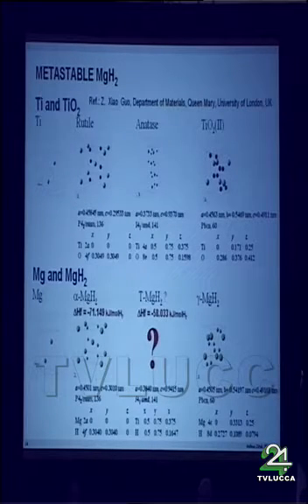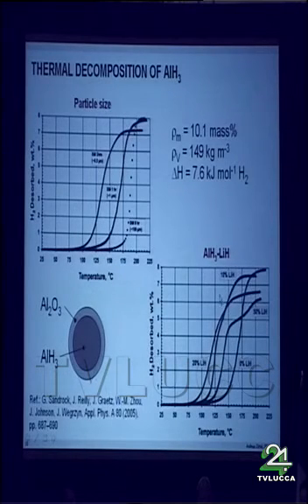Then there is always, already since quite a time, this discussion about the metastable magnesium hydride phase. When you compare magnesium and magnesium hydride with titanium and titanium oxide, there is a strong similarity in the structures. And titanium oxide forms this anatase structure, but this structure wasn't found experimentally for magnesium hydride until now. However, theoretical calculations predict a much lower stability of the hydride in this phase. And therefore, of course, it would be interesting to synthesize this magnesium hydride phase and measure its properties.